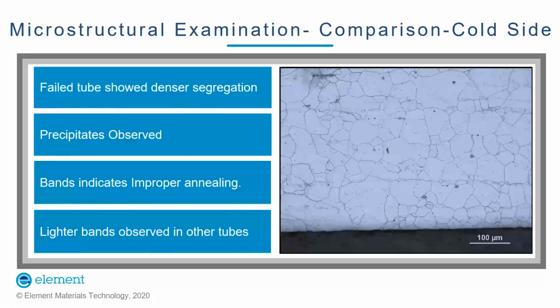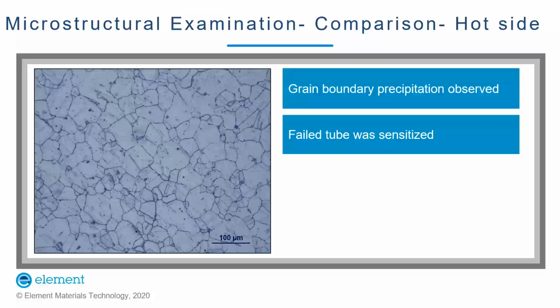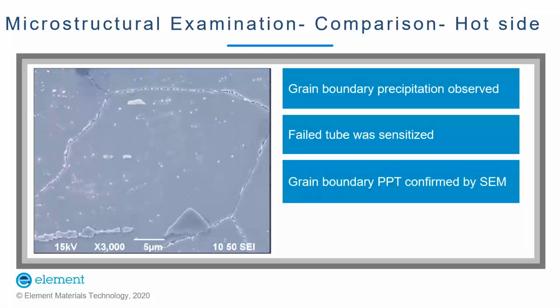Similarly, the microstructure of the failed tube at the hot side showed heavy grain boundary precipitation. It was very clear that the failed tube was sensitized under adverse conditions of operating temperature and pressure. At high magnification, we did an electron microscopic analysis of this precipitation, and it confirmed there was precipitation.